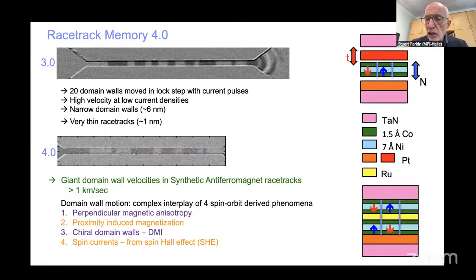The structure of that racetrack consists of a cobalt, nickel, cobalt sandwich, where the cobalt layers are roughly 1.5 angstroms thick, and the nickel layers 7 angstroms thick. So the magnetic layer thickness in this racetrack is 1 nanometer. And the platinum layer underneath, which is used to provide the spin orbit torques, is just 2 or 3 nanometers thick.